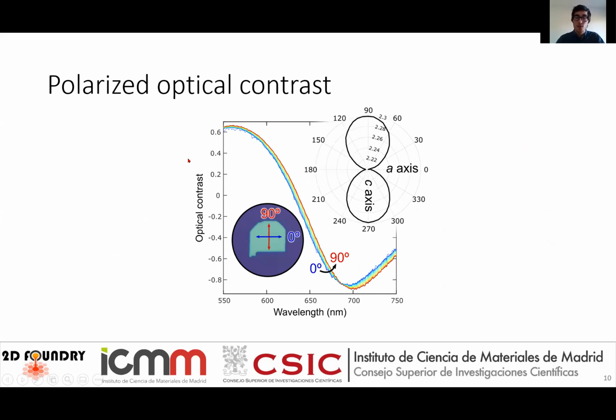But apart from it, you can use a simple optical microscope with polarized light as well. And you can rotate this linearly polarized light along the 360 degrees. And you can see a shift in the wavelength if you rotate this angle. Here it is plotted with a stereographic plot. It is the difference of refraction index that you get along this angle. And with this method, you can also determine which direction belongs to the flake you're looking at. So the c-axis belongs to the direction of the highest refraction index.